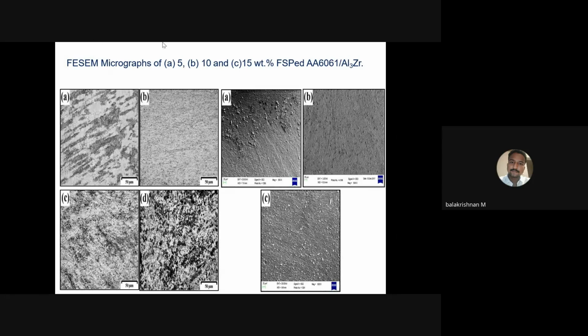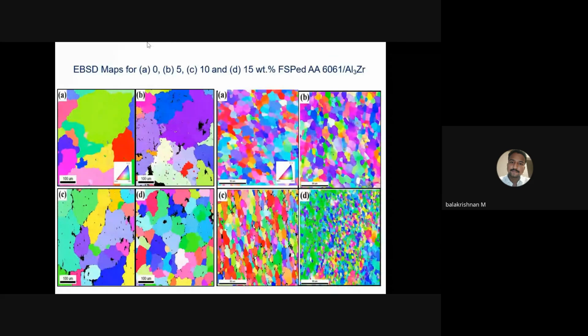So here we can see that the particles are finely refined along the grain boundaries. The grain boundary is also refined very well after friction stir processing. Here compared to Al3Zr...